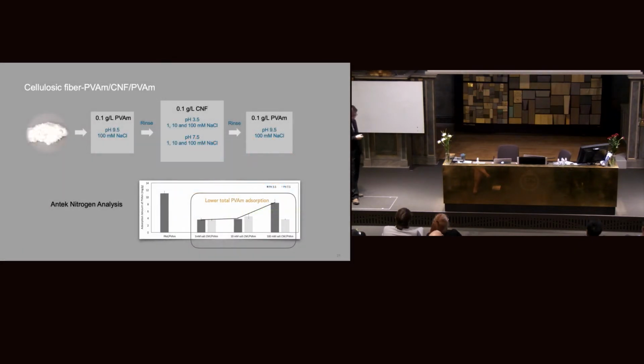To evaluate this, I modified the pulp by first depositing 1 layer of PVAm, then used different pH setups and salt concentrations to find the optimized adsorption condition for CNF deposition. The third layer still kept PVAM.